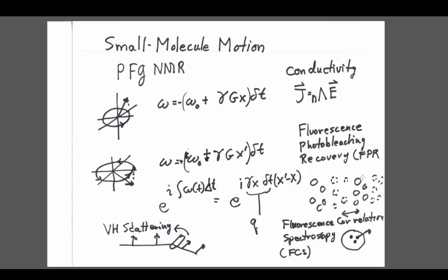We now blast the solution with a high-power laser beam, and the high-power laser beam bleaches the dye in some areas. A standard pattern of bleaching is stripes. And so the solid circles are molecules that are currently not bleached, and the round open circles, the dashed circles, are molecules that are bleached. We now sit and measure, and what happens as time goes on is that the bleached and unbleached molecules switch places, and as they do, this concentration gradient, fluorescent and not fluorescent, gradually goes away.